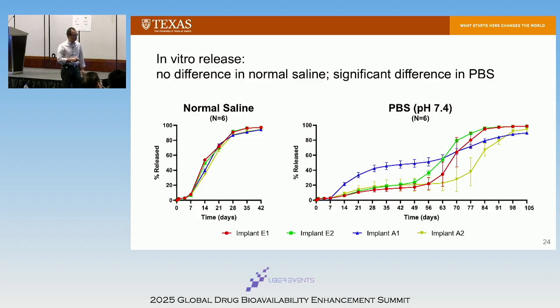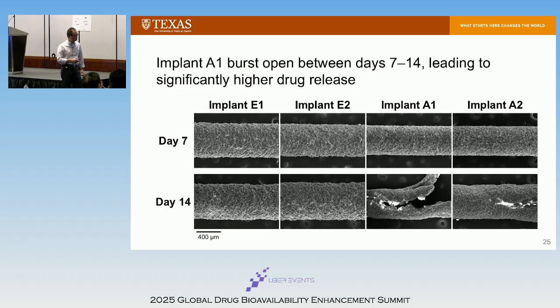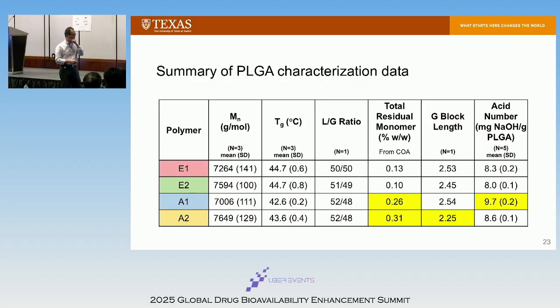And one of the questions is why at that time, we're puzzling. So we look a little bit closer, we find out with more blocky ones, the implants actually will split during the dissolution test. We believe the reason is because of the difference in the residual monomers and higher acid values, okay?